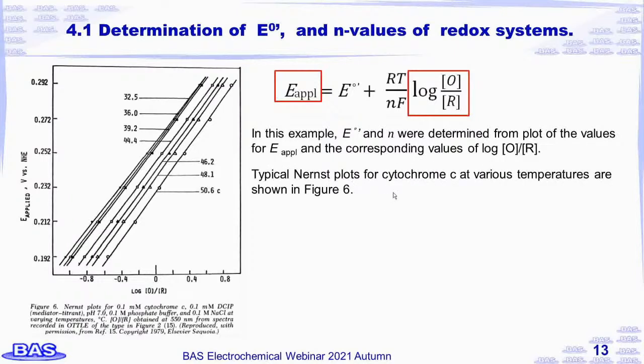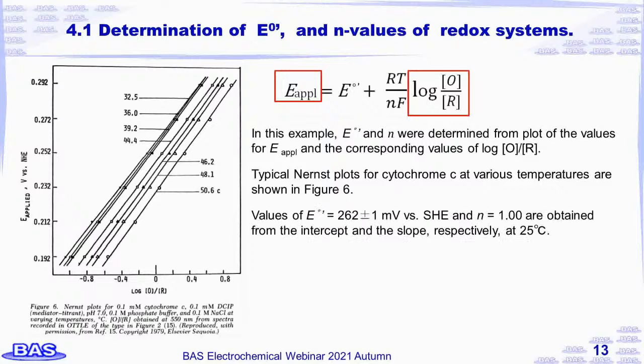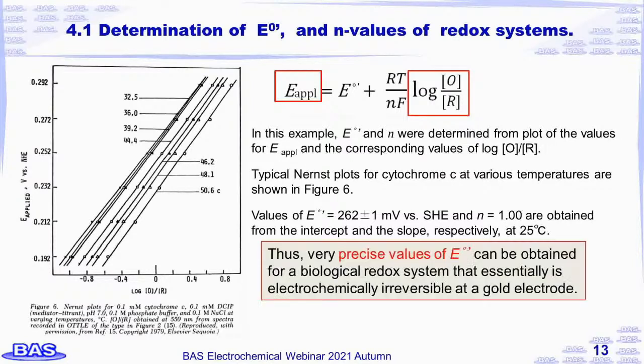Typical Nernst plots for cytochrome c at various temperatures are shown in Figure 6. Values of E°' equal to 262 ± 1 mV and n equal to 1 are obtained from the intercept and slope respectively at 25 °C. Thus, very precise values of formal reduction potential can be obtained for a biological redox system that is essentially electrochemically irreversible at a gold electrode.